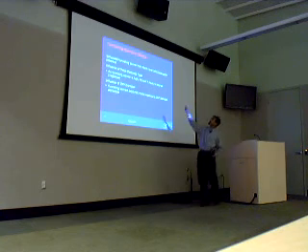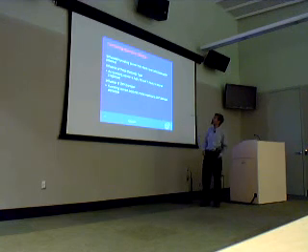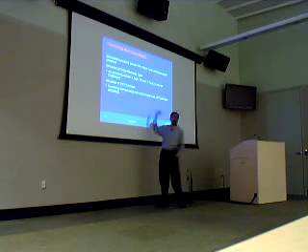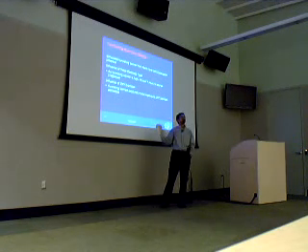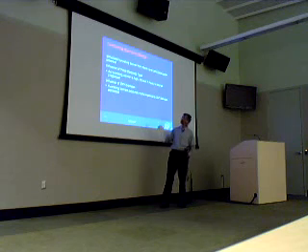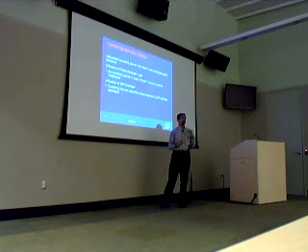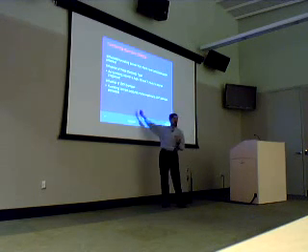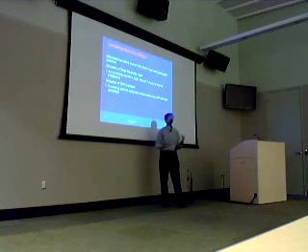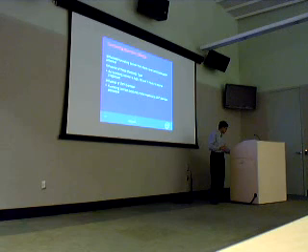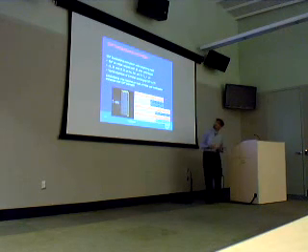So the first thing we did was we essentially simulated the barrier effects, and we found out that the tunneling barrier becomes more negative as CNT diameter decreases. So this will not explain it. What this means is you actually have no barrier when the CNT becomes very small. So you do not necessarily have this contributing to the reduced conductance for smaller diameters. So that's the first study we did.